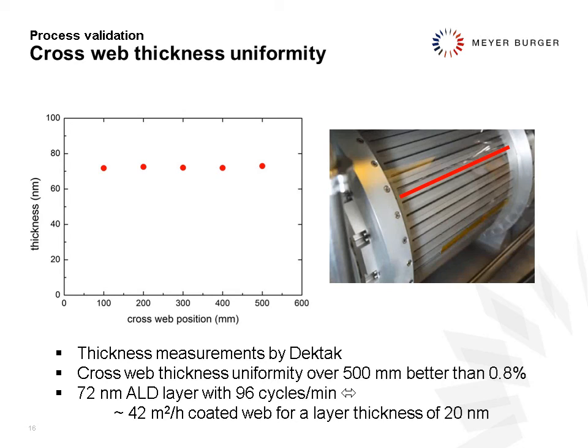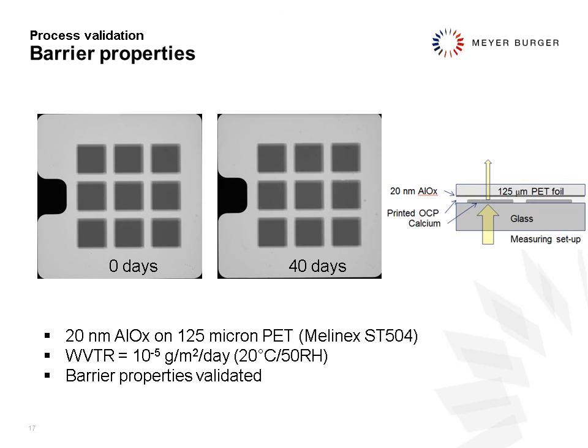This will ensure almost intrinsically uniformity. It depends on gas showering and so on, but these are all mechanical things that we can handle, we have experience with. So the uniformity is some sort of present you get from the construction. And what we demonstrated is that it was possible, like in this case, to make 72 nanometer of ALD with 96 cycles per minute, which, if you count a layer thickness of 20 nanometer, which would be enough for a barrier, means you can coat 42 square meter per hour, which is quite a good achievement.